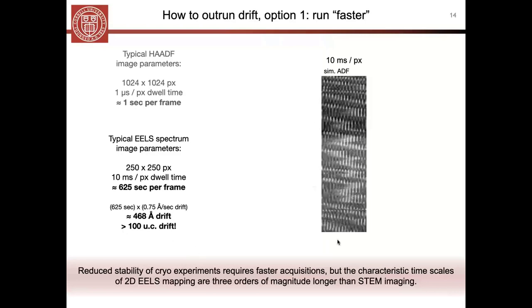And so if you want to know what that looks like, having tried it, the argument for preserving a two-dimensional atomic localization in this, a simultaneous ADF image from a cryogenic EELS map with these dwell times, I think is basically lost, right? So there's no more spatial localization preserved in this EELS map.